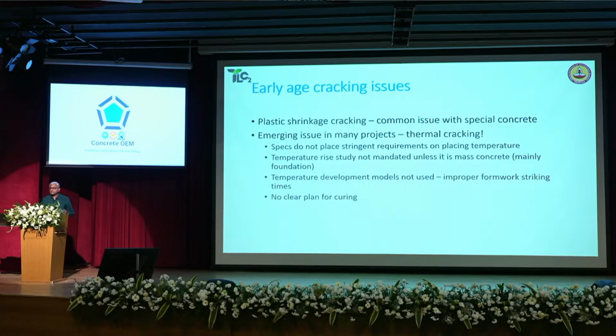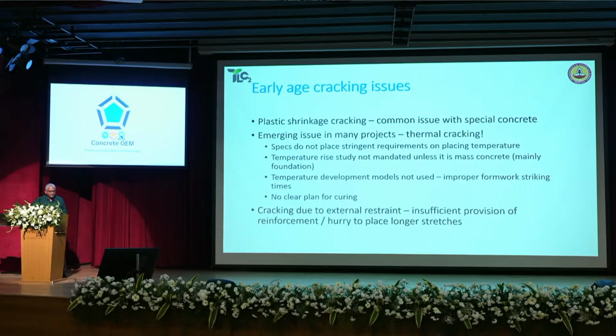Because again, one more aspect that Professor Gettu alluded to was that you can actually insulate the members to ensure that the heat loss does not happen from the sides and that the temperature differential can be minimized. So here, in massive structures, it often helps to keep the formwork on for as long as possible to ensure that heat does not get dissipated fast. And it's preferred to use plywood formwork instead of steel to ensure that the heat does not go away very rapidly. And there is no clear plan for curing. Very often we look at all these massive concrete structures also where simply they remove the formwork, start pouring water directly. The problem is if you already have a temperature differential, pouring water is going to increase the temperature differential and you'll certainly get cracking.